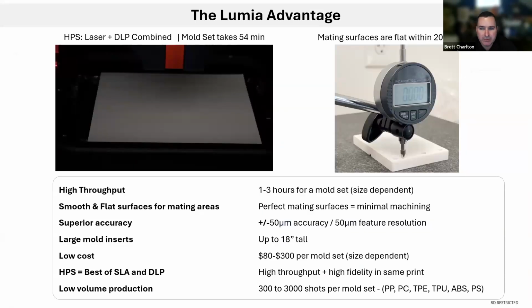Let's talk a little bit about the advantages of the Lumia system as we have seen them for our molding application. First, there is high throughput. Our case study allowed us to produce the complete mold set in under an hour. And if I had wanted to print another set, it would have fit right on the platform and not added any additional print time. It never hurts to have an extra, especially when you need to dial in your process at the beginning. To date, the largest mold set we have produced has measured around 5 inches by 6 inches in the X and Y by about 2.5 inches deep. That mold half took roughly 2.5 hours to print.